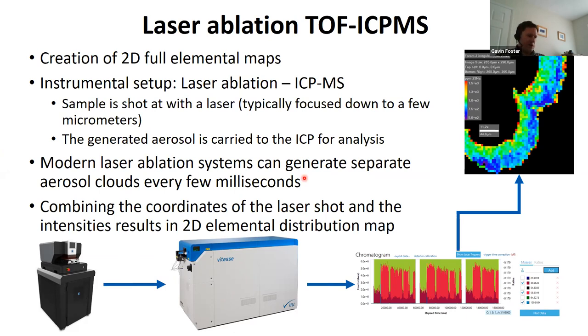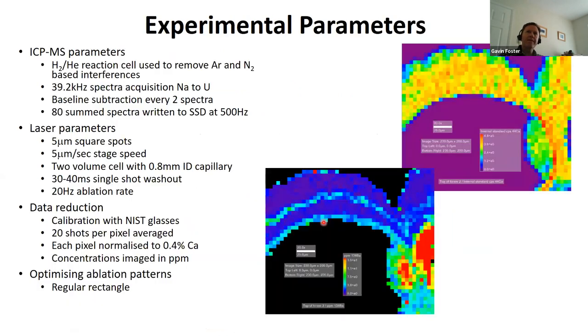You coordinate the push out and the extraction of ions in the Vitesse with the shots of the laser. And because you drag the laser beam across the surface of your sample, you then are able to coordinate those and generate a 2D elemental distribution map. And because we're looking at TOF, we can go from sodium up to uranium almost instantaneously. For those of you interested, we used hydrogen helium reaction cell gas to remove argon and nitrogen based interferences, full spectra from sodium to uranium, baseline subtraction, and then these 80 averaged spectra are then written to the hard drive.